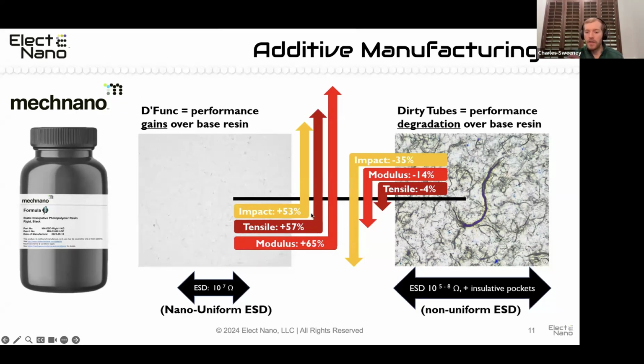When you do that right, you get very consistent electrical properties. Your mechanical properties go up: impact goes up, tensile modulus goes up, tensile strength goes up. If you do it poorly, if you just take nanotubes and mix them in, you're mixing a bunch of defects in. You may get some electrical properties, but they're all over the place in terms of variation. You've got resin-rich and carbon nanotube-rich areas, and that creates a lot of variation in the electrical properties of the material. And usually all your mechanical properties go down because you've basically stirred defects into your component. Especially with SLA, because of the process, if you have areas that are over-curing and under-curing all over the place, it leads to very non-uniform final properties in your 3D printed parts.